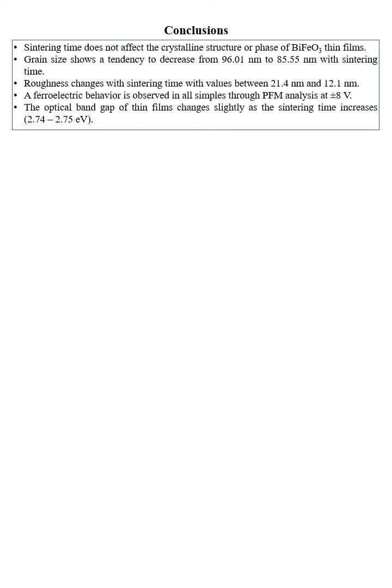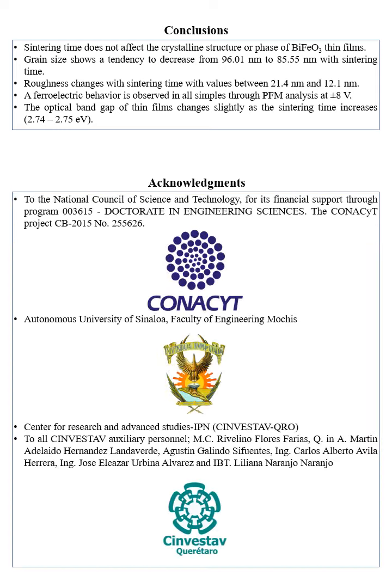Conclusions. Sintering time does not affect the crystalline structure or phase of bismuth ferrite thin films. Grain size shows a tendency to decrease from 96.01 nanometers to 85.55 nanometers with sintering time. Roughness changes with sintering time with values between 21.4 nanometers and 12.1 nanometers. A ferroelectric behavior is observed in all samples through PFM analysis at ±8 volts. The optical bandgap of thin films changes slightly as the sintering time increases.